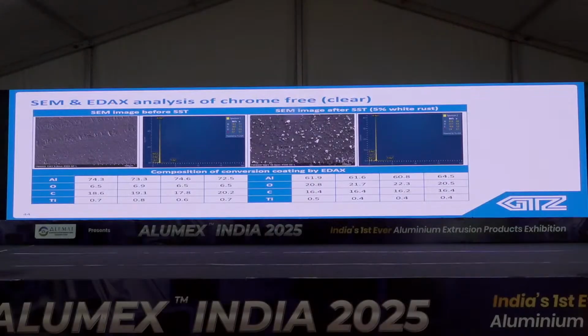On the first left side is the same picture of the coating before SST, salt spray hours. And this is the EDS spectrum for elemental composition. We have selected 3 areas and the composition is given there. So before salt spray, you just check the chromium content. It is average 7.7%, and after SST 5% white rust, it becomes average 4. So titanium is washing out after salt spray, and titanium is the major contributor to the salt spray hours.